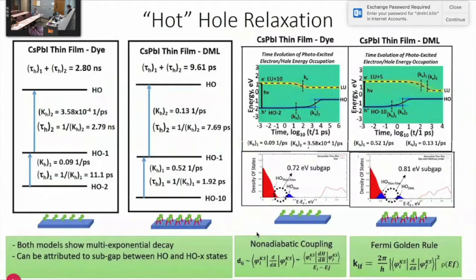And then on the left is just a more conventional illustration showing the rates and the times between each of the transitions. So we can see for the HOMO -2 to HOMO -1, for the dye system, it takes about 11 picoseconds. And then for the HOMO -10 to HOMO -1 transition in the DML, it takes about 1 picosecond. So there's roughly an order of magnitude difference, but nothing dramatic between them.